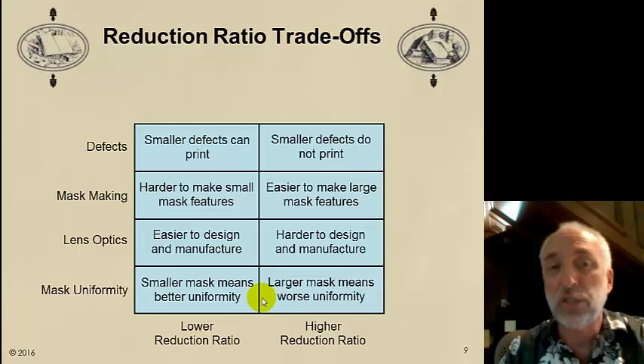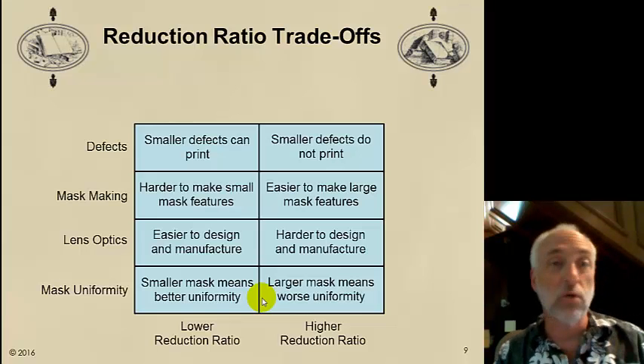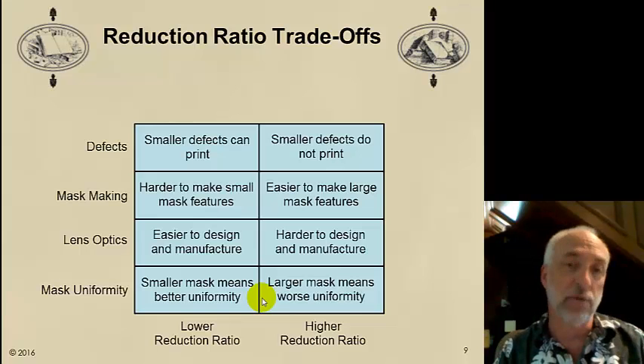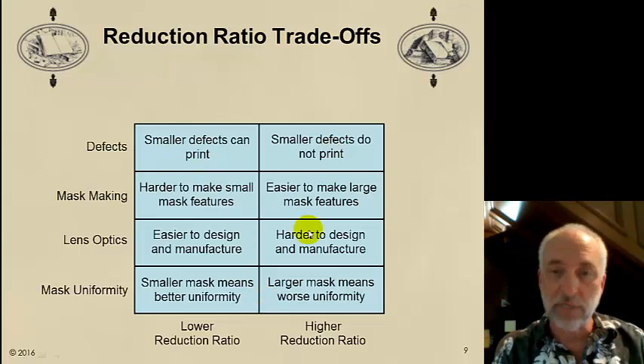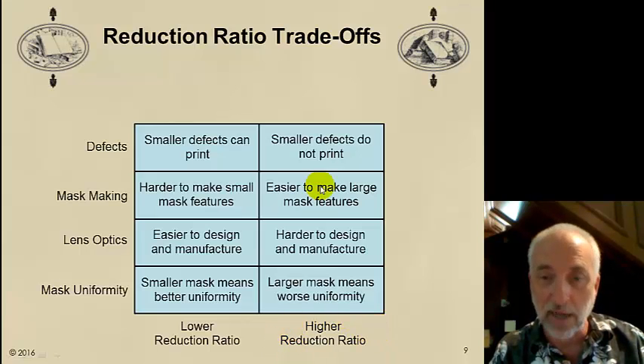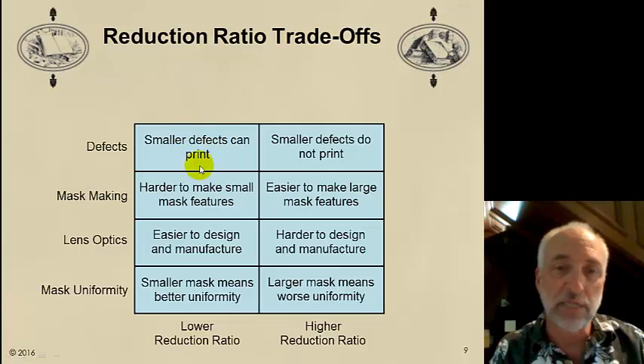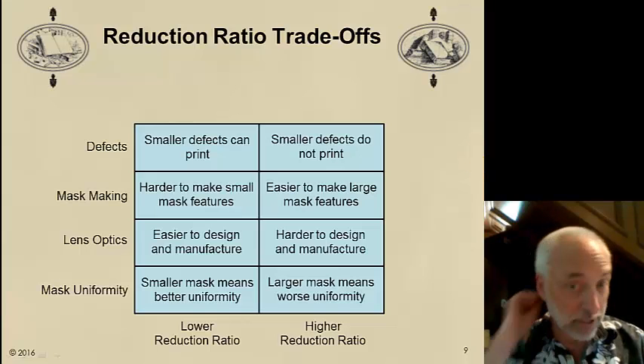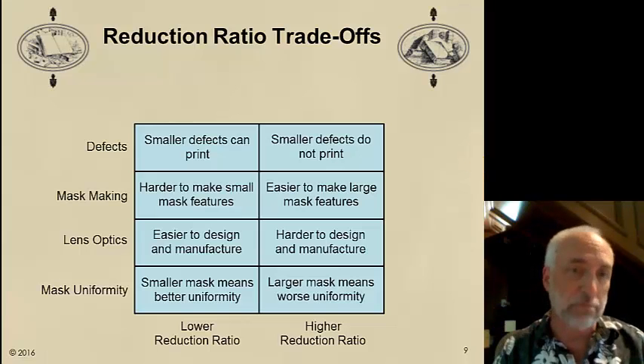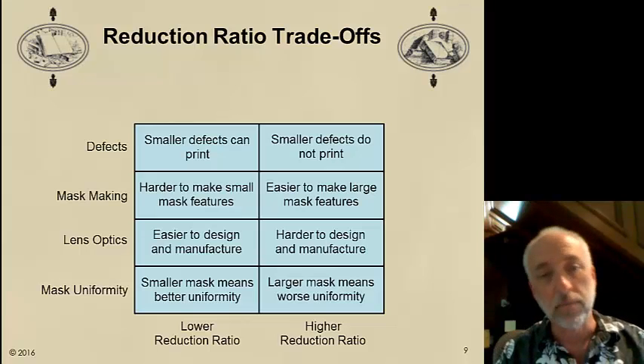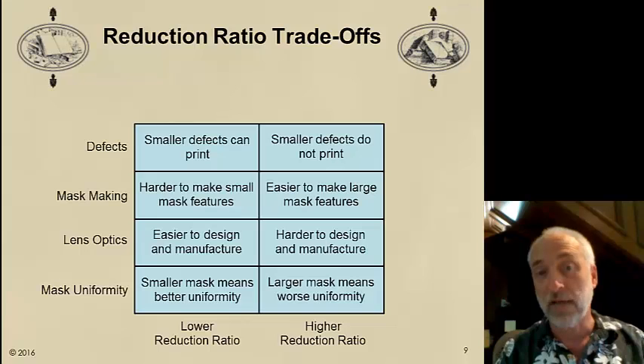Well, one important issue is the printability of defects. If we have a defect that lands on the photomask, any reduction ratio will reduce or shrink the size of the defect that we have as well. Therefore, if I have a higher reduction ratio, here, the right-hand column, then some smaller defect won't print because it'll be shrunk by this higher reduction ratio, whereas maybe that defect would print at a lower reduction ratio. Well, that kind of pushes us to want to use higher reduction ratios in order to get less defect printability. But there's other factors as well.